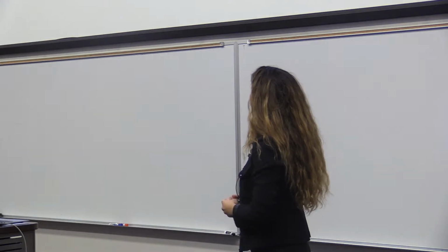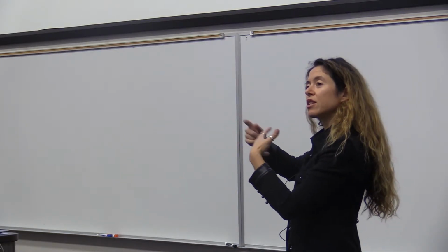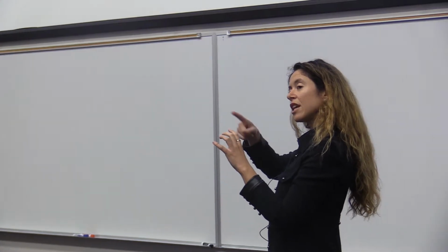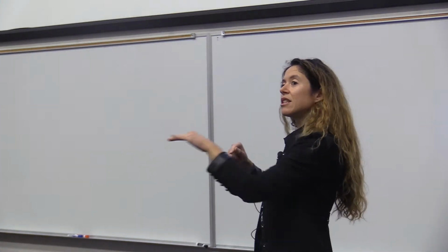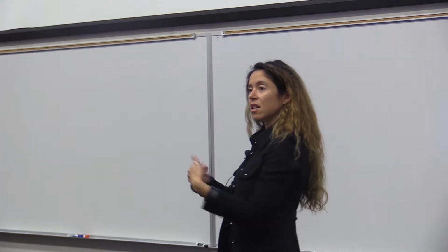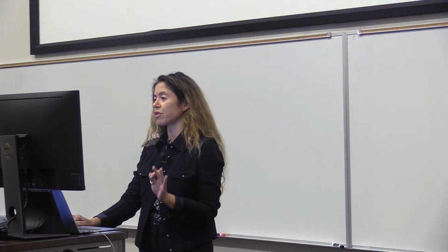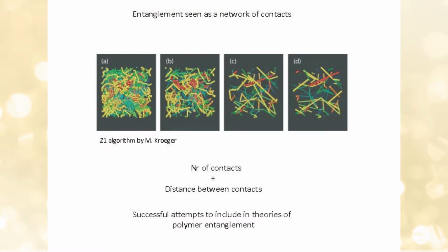By creating this tube, one can measure the width of the tube, let's say the radius, and see from that what the different critical times for the motion are. Diffusion within that radius, and then the time it takes for it to reptate, to go out of this tube and find its way out of the entanglements. So this simple idea has been very useful in describing polymer response.